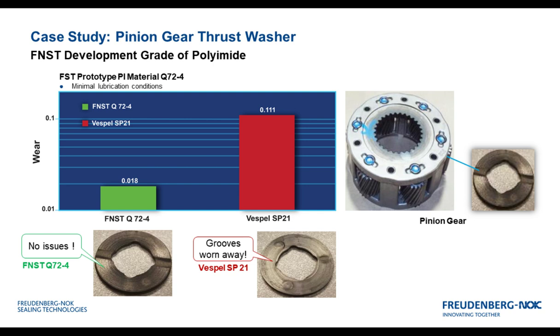Here's a case study we did where we actually took a part that's being made in production today and tested it to validate our wear performance methods could be measured. In this case, we're looking at a pinion gear application. The part in production has a couple of grooves in this washer that's used between these pinion gears, and it's made out of the Vespel SP21. This material is a very high temperature material, used often in very low lubrication conditions. We ran that on our test stand, and you can see we got a wear rate that was quite large, 0.11. That material actually wore away and would not pass the 4-hour test condition that the test was designed for. And you can see in the picture, no grooves are left from the wear.